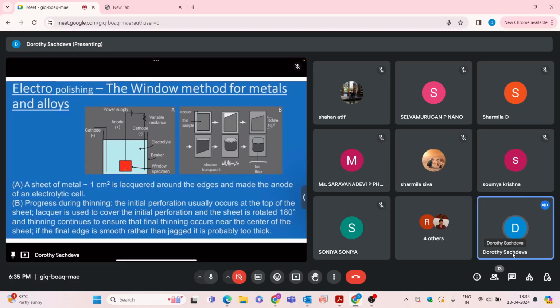This is just the detail of the electropolishing method. Just a sheet of metal which you want to thin, around 1 square centimeter, is lacquered around the edges and made the anode of an electrolytic cell. During thinning, the initial perforation usually occurs at the top of the sheet, at this side, as shown here. The lacquer is used to cover the initial perforation, and the sheet is rotated 180 degrees to have your thinning at the bottom part itself, and then the thinning continues to ensure that the final thinning occurs near the center of the sheet. If the final edge is smooth rather than jagged, it is probably too thick.